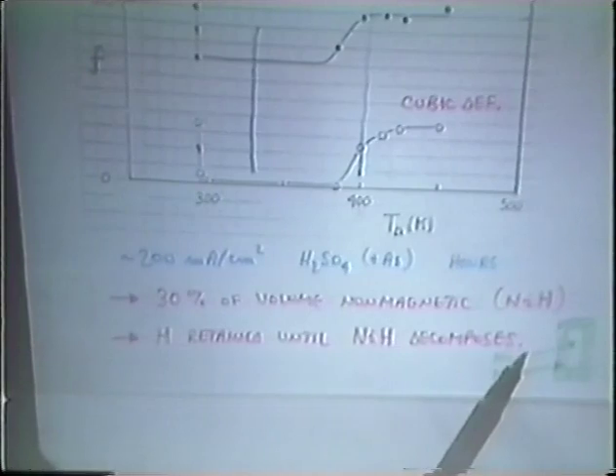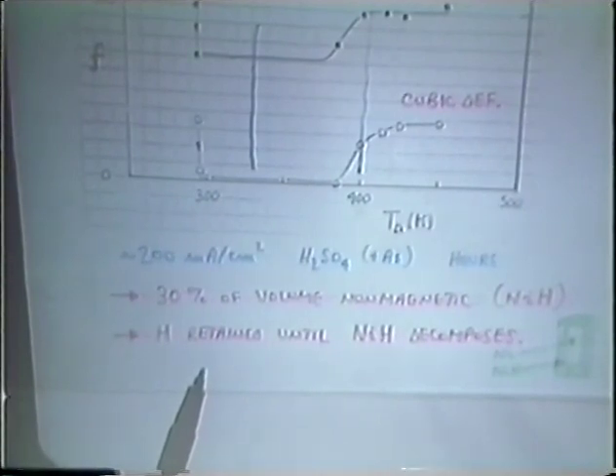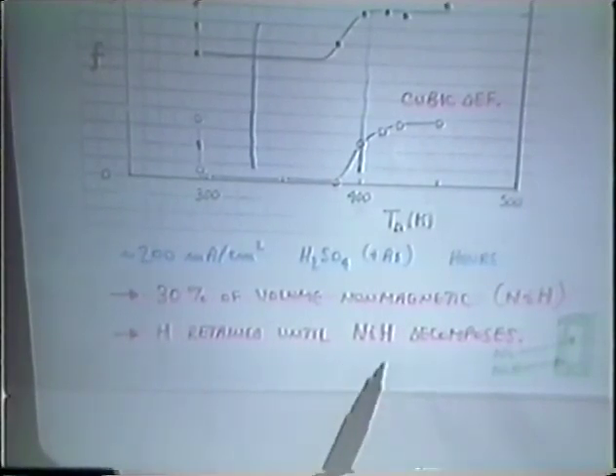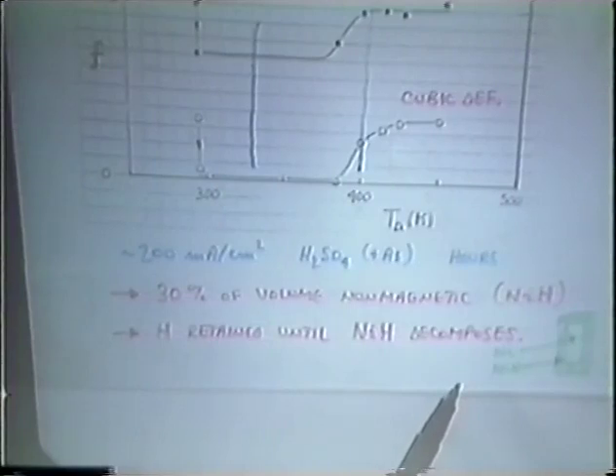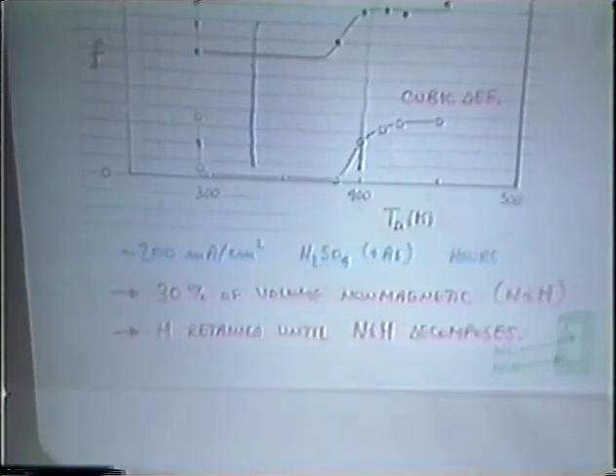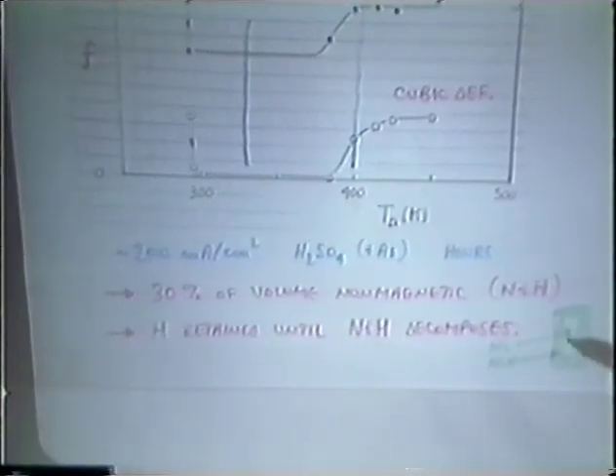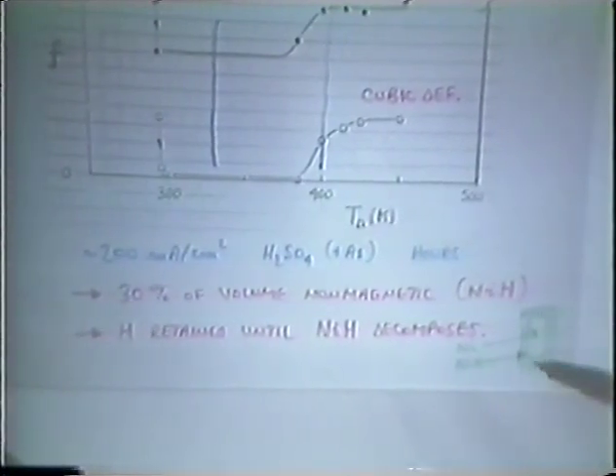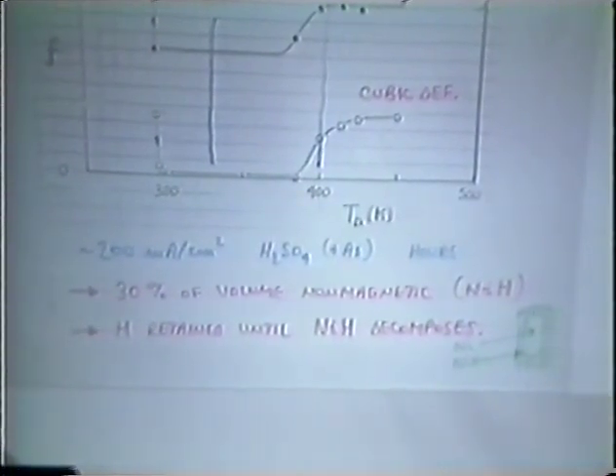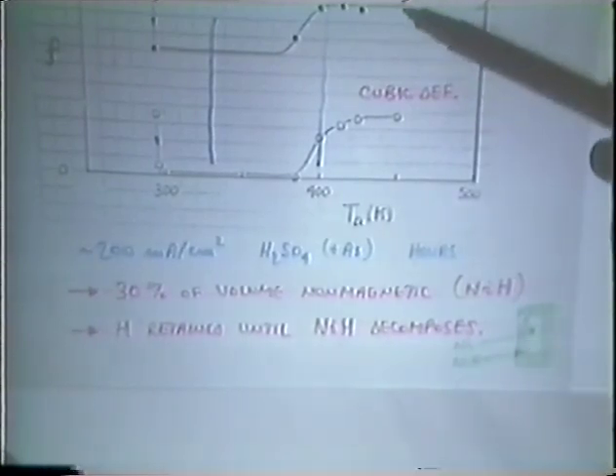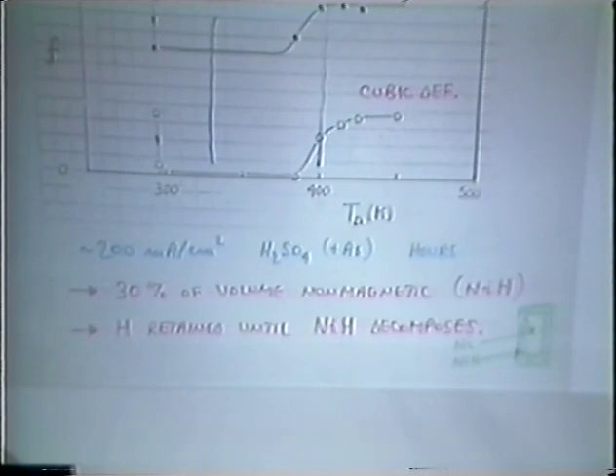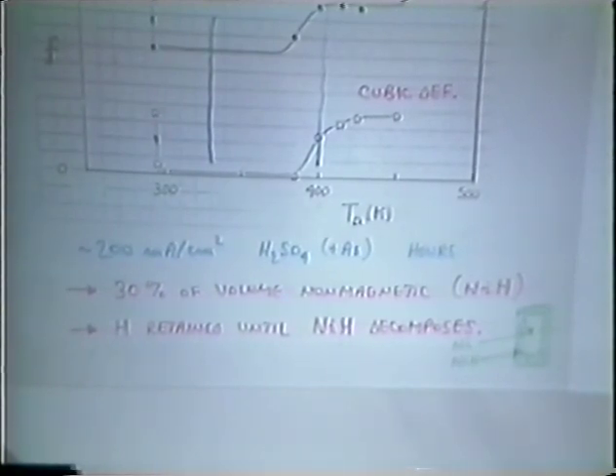We attribute this to 30% of the volume of the sample becoming non-magnetic. Nickel hydride is non-magnetic. And that the hydrogen is retained by the nickel hydride, which probably forms at the surface, until the nickel hydride decomposes, in effect decomposes around 400 K. In other words, we have a sample with nickel hydride at the surface surrounding nickel at the interior. So at the interior, you still have cubic defect-free substitutional lattice sites. This is our evidence for nickel hydride.